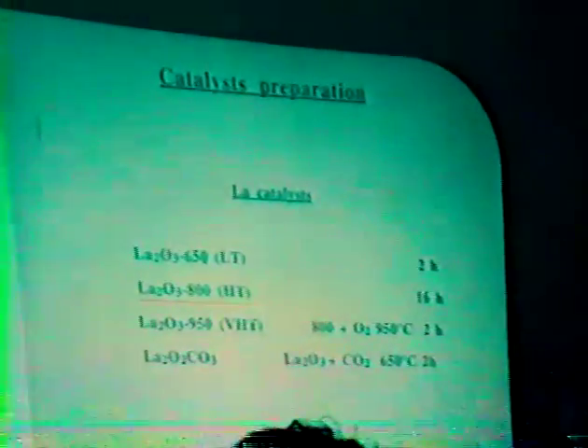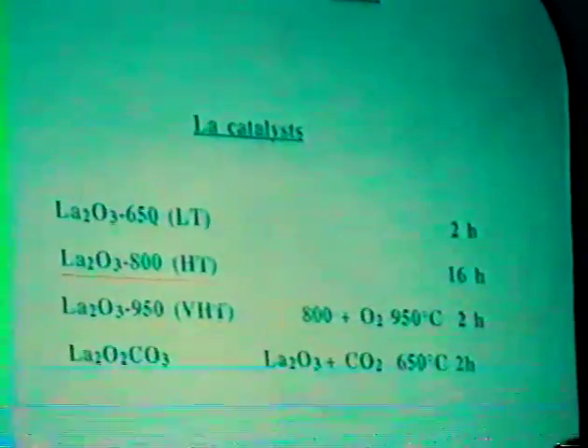The lanthanum catalysts are prepared from the thermal decomposition of the nitrates in air at several temperatures. Here is indicated the low temperature, high temperature, and very high temperature thermal treatment. You will see later that this treatment is important to give a special morphology of the catalyst for improved selectivity to C2+. We have used also tungsten-doped lanthanum catalysts for this study, prepared in the same way.